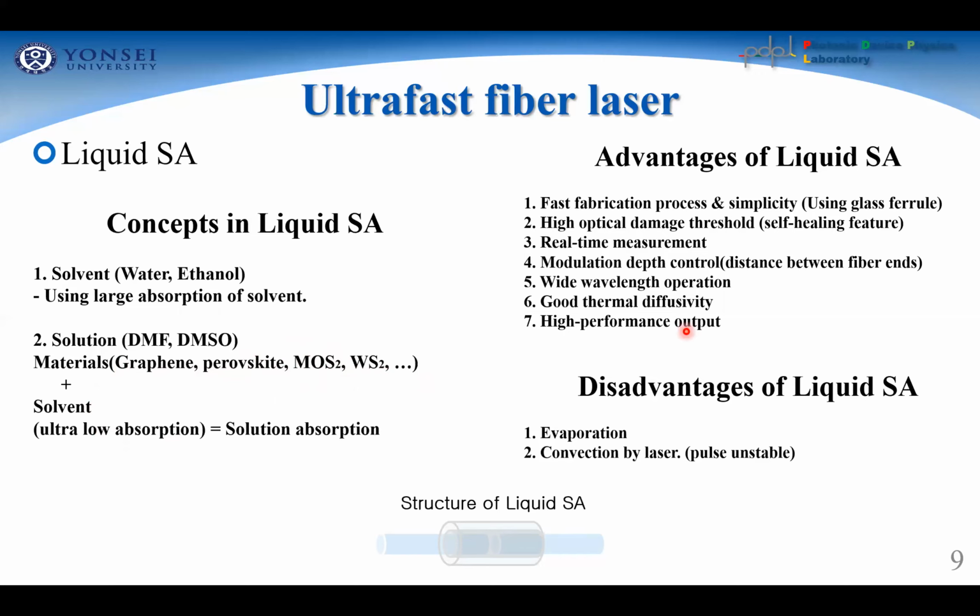The advantage of the liquid saturable absorber is the fast fabrication process and the simplicity of its fabrication. It also has a high optical damage threshold because of the self-healing features of the liquid, and we can see real-time pulse laser measurements.